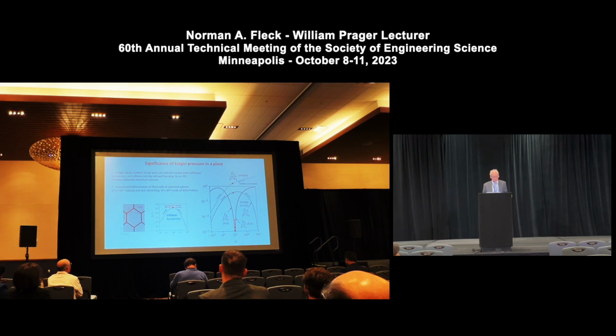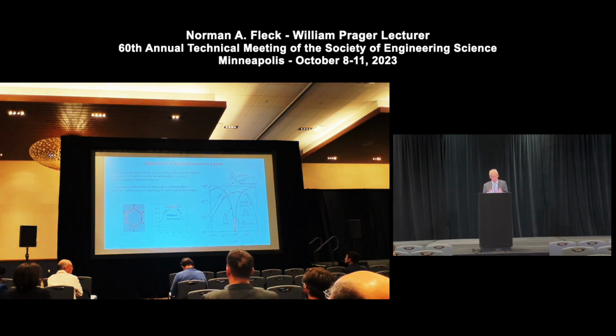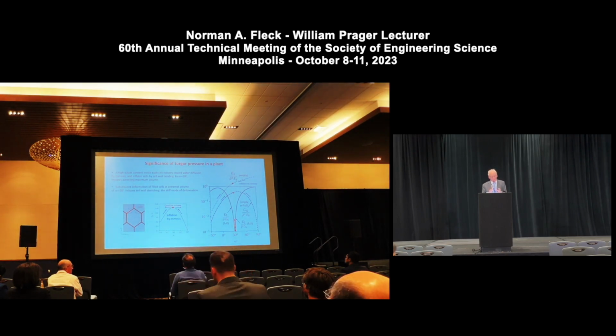One way to think of this is in the flaccid or in the relaxed state, where omega is not 30 degrees. The plant cell has a smaller volume. When osmosis comes along, water diffuses into the cells, the cells inflate and they would like to go to this inflated state of 30 degrees for omega. And once they get to this inflated state of 30 degrees, the structure is then fully inflated, and the only way it could continue to deform is by a deformation mode which involves stretching of the structure.